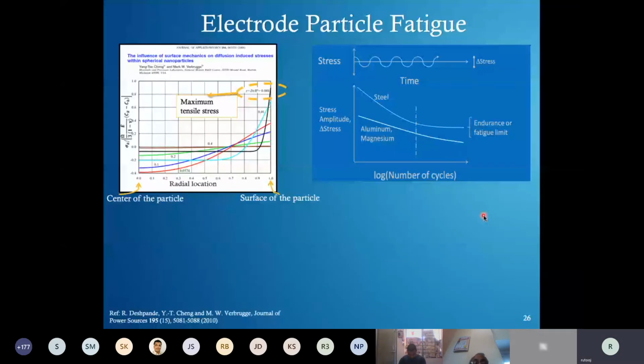Now you can basically calculate the diffusion-induced stress at different times. For example, this is 0.01 normalized time, and this is 0.4 normalized time. So at different locations within the electrode particle, you would have different stresses. There are positive stresses, which are tension, and there are negative stresses, which are compression, on some parts of the electrode particle. Now, each time you are charging and discharging your cell, each of your electrode particles is seeing some positive and negative stress. So there are tension and compression cycles that it is experiencing.